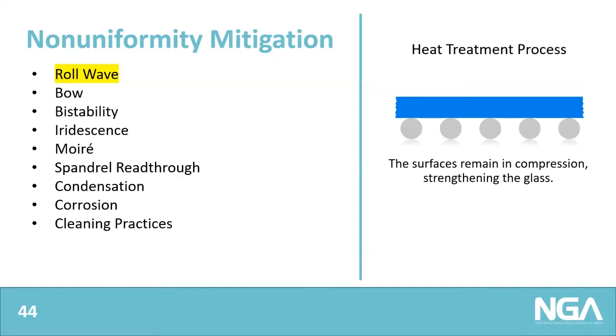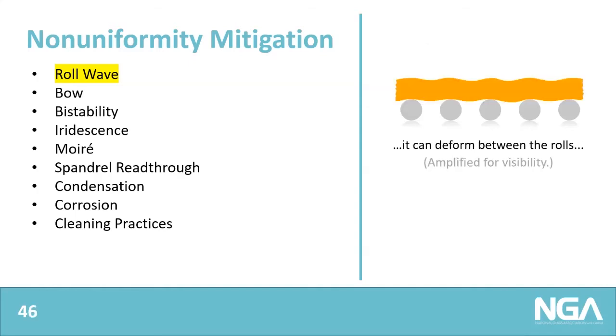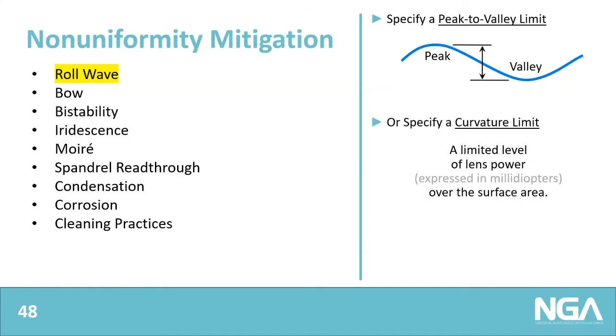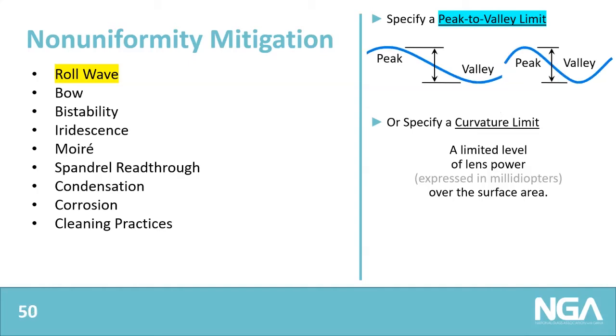Now, the issue in regard to roll wave is that as the glass is heated, it can deform between the rolls and then remain permanently deformed. As you can see written there, this is amplified for visibility, highly amplified. If we amplify it even further, we can see we clearly have a waveform. And so one way of navigating roll wave is to specify a peak to valley limit. The shorter the peak to valley limit, the flatter the glass. Now this does have its own constraint, and that is we could have multiple geometries with the same peak to valley dimension, the flatter ones being preferable to the more abrupt curves.